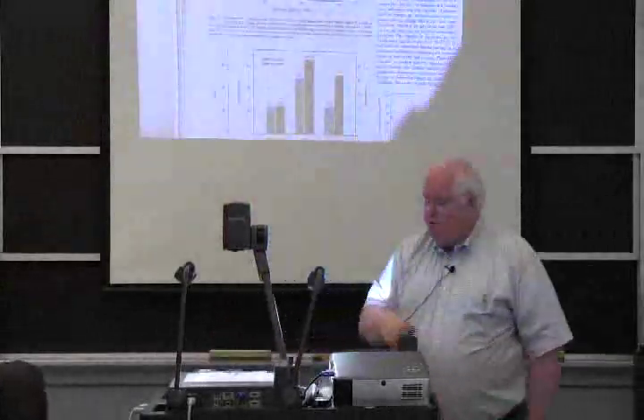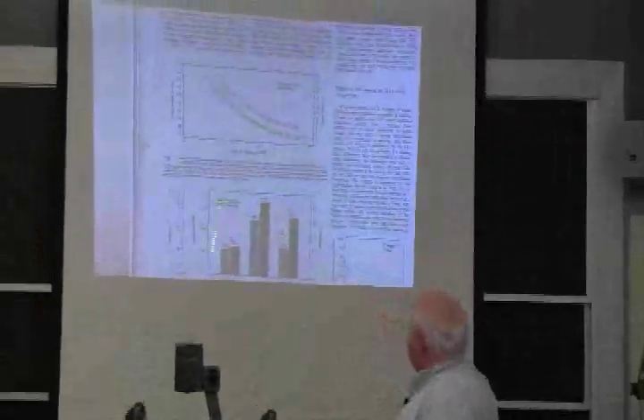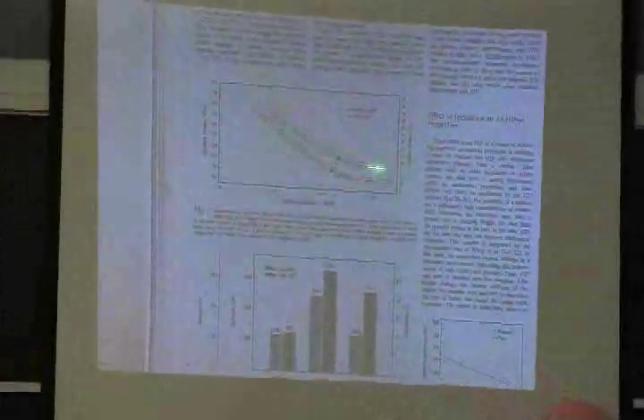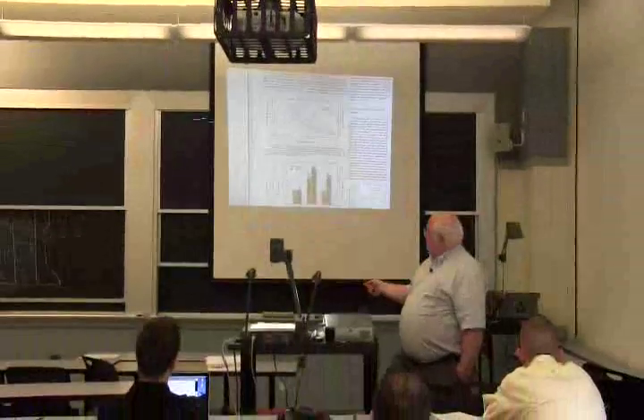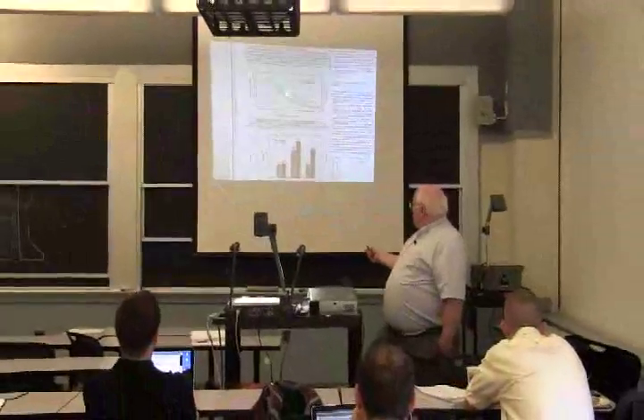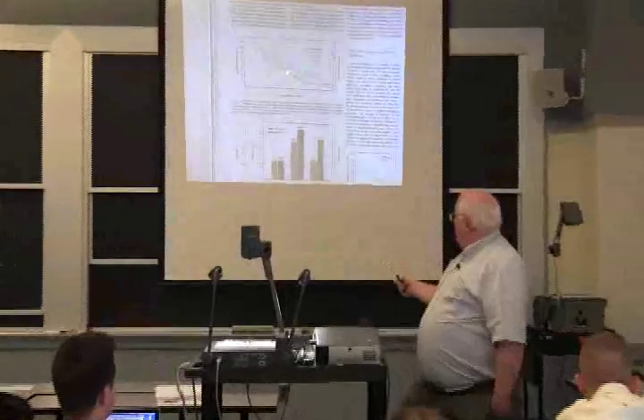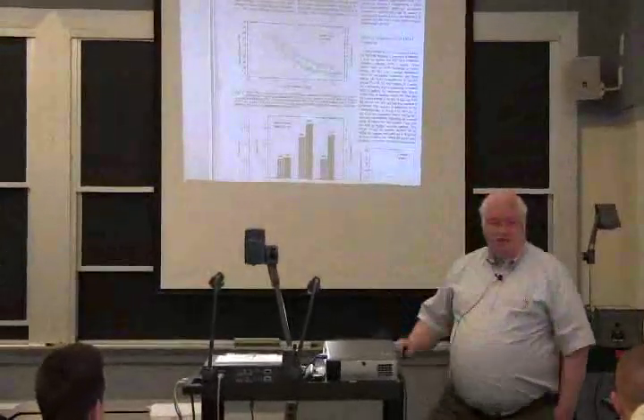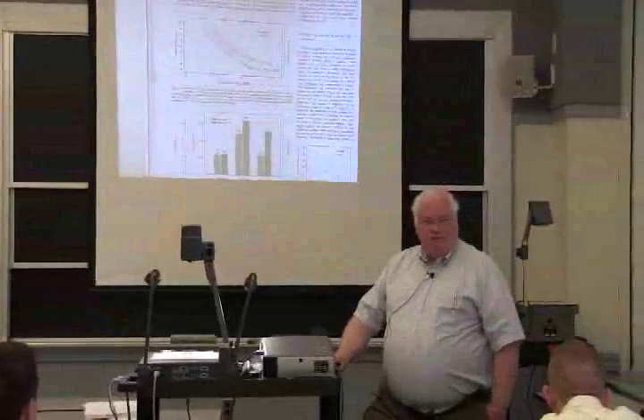For hipping, you can get dramatic improvements in properties such as fatigue properties. This is applied stress versus cycles to failure, so this is just a fatigue curve, and you actually go up by about 20% in stress. But 20% in stress in terms of fatigue life is like a factor of 400% in life, because of the slope of that curve. In high cycle fatigue, you get some very large increases in life.